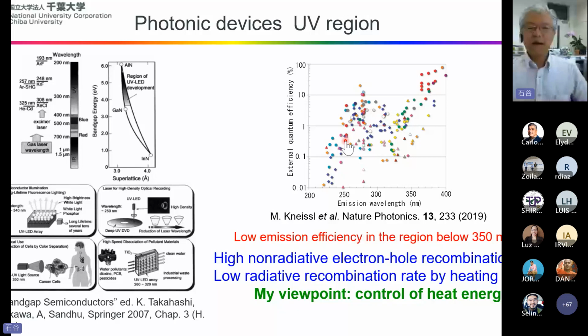This is because of the high rate of non-radiative electron hole recombination. And people are now focusing on this point, mainly focusing on this problem. But actually, the low radiative recombination rate by heating is hindered. So my viewpoint is that controlling the heat energy is very important to enhance the recombination probability itself.